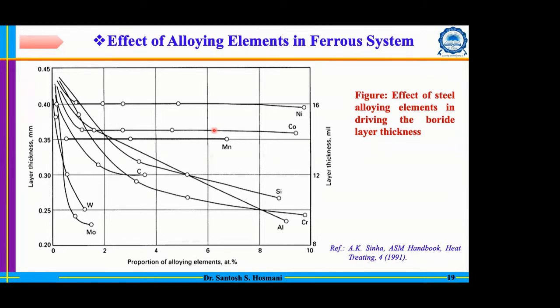However, this restriction, whatever is shown here, is basically associated mostly with binary systems. But in reality, whenever you have the presence of multiple components, the behavior of these elements will be entirely complicated, and probably it may not behave as actually shown on this screen. But broadly speaking, carbon, silicon, aluminum, chromium restrict the boride growth, and manganese, cobalt, nickel don't have much effect on the growth of boride.